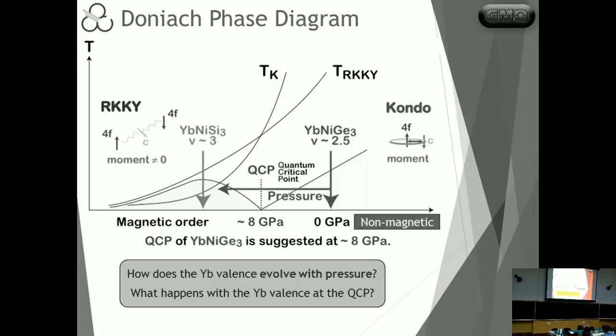So the general picture that we get from this is that if we look at the Doniach phase diagram, we're going to have the typical bell curve of the Doniach phase diagram. Here around 8 GPa, we have the supposed quantum critical point. Ytterbium, which has a high Néel temperature, should be around here near the maximum. So when we apply pressure, in this case, it goes in this direction. But the nickel germanide should be around here, and with enough pressure then we might go into this region.